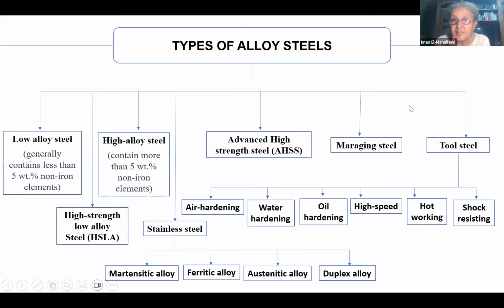Generally, when we talk about alloy steels, in addition to the main definition, in which we have just said that they contain other alloying elements, we can classify them into different groups. We have the conventional low alloy steel, which usually refers to those iron carbon alloys with ranges of alloying elements less than 5%. And we have the high alloy steel, in which we add higher than 5%, maybe up to 50% of those other alloying elements. But I say up to 50% because, of course, the remaining has to be 50% iron, because they are still called steels. Otherwise, they would be called something else. For example, if nickel is higher than 50%, then they will be no longer steels.